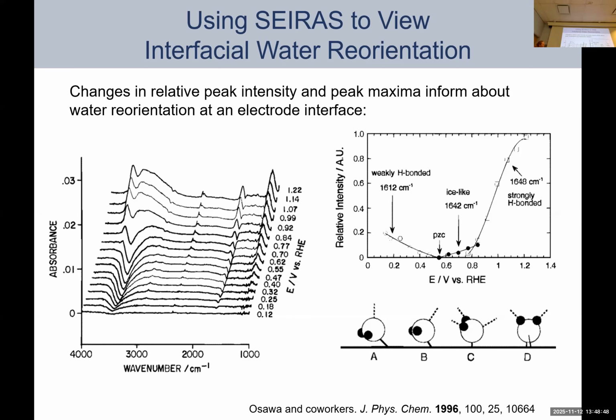Well, the explanation comes from the fact that the water molecules, you think about, these are not eyeballs, these are water molecules, the 2 H's in black and the O in white. There's actually a reorientation that's potential dependent. So at potentials sort of out here more close to, let's see, more positive. The oxygen of water is actually, oh, sorry, no, this is more negative. I'm confusing myself on this axis. At more negative applied potentials, you have the water sitting in a horizontal location, so the hydrogens are almost flat with the surface. And then as you polarize your electrode to more positive potentials, the water molecule actually spins around. So now you have the delta minus of the oxygen pointing more directly towards the surface. Okay, and so these changes in solvent orientation can actually be measured spectroscopically. So that helps paint a fuller picture of what solvent specific changes might be happening.